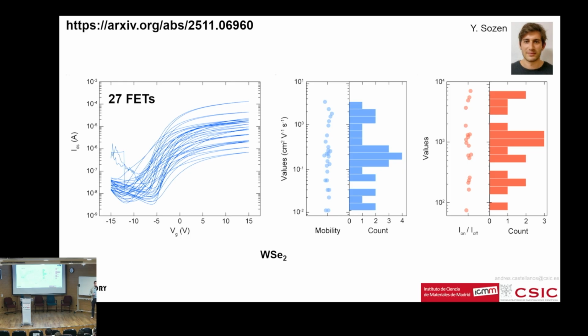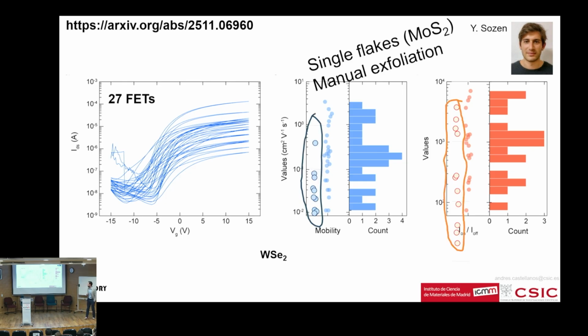I would like to stress that you can get despair by this kind of long dispersion in the values of mobility and on-off ratios. But luckily for us, we've been fabricating field effect transistors with single flakes, carefully mechanically exfoliated, manually placed in the position you wanted. So I went all the way to Pablo Bastante's thesis, and I took, if I remember correctly, 10 or 12 different molybdenum disulfide single layer transistors. And you see that basically the values have the same kind of dispersion.